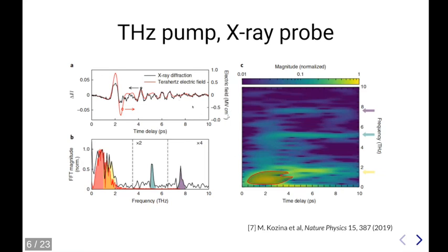And if you Fourier transform this signal that they got, you can actually see that even if you pump a frequency which is very low and is in resonance with the soft ferroelectric mode of this material, they are able to excite higher frequency modes at 5 and 8 terahertz, here displayed by this plot in which they use a variable size window on the time to get a time-resolved Fourier transform of the signal.